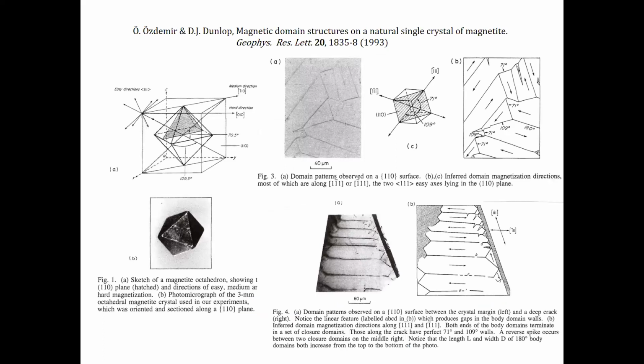Back in rock magnetism, Özdemir in the 1990s embarked on a long series of studies of magnetic domain structure revealed by Bitter patterns, which show the intersection of domain walls with a polished surface. And these photos are absolutely the best that have ever been published for magnetite, and among the best for any mineral. The trick here is to section a crystal exactly along a 110 plane, which sounds easy, but it's not. This was the kind of thing that Özdemir could do. I could never have done, I'm sure.